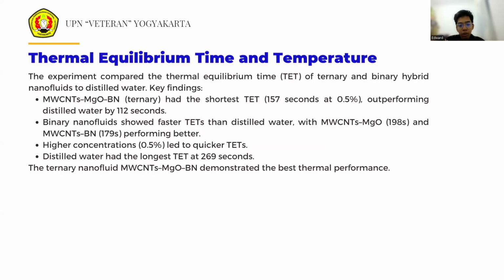Binary hybrid nanofluids: equilibrium time of 198 seconds at 0.5%, 71 seconds faster than distilled water. MWCNTs with boron: equilibrium time of 179 seconds at 0.5%, 90 seconds faster than distilled water. And we have magnesium oxide with boron: equilibrium time of 230 seconds at 0.5%, 39 seconds faster than distilled water. The third, volume concentration impact: higher volume concentration at 0.5% consistently reduces TET compared to lower concentrations for all nanofluids.